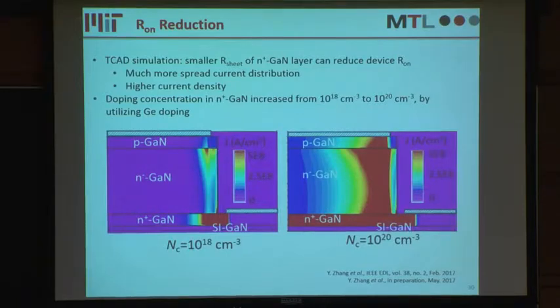Here I show the simulated current density in 2 structures. The structure on the left has a doping concentration of 10 to the 18 in the N+ gallium nitride layer, and on the right it's 10 to the 20. As you can see, the current is much more spread out in this structure, and the current density is also higher, meaning the on-resistance is lower.